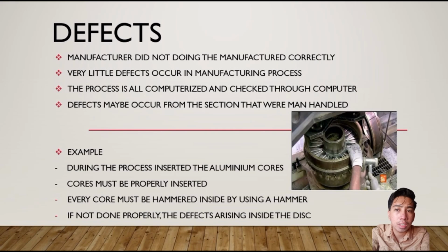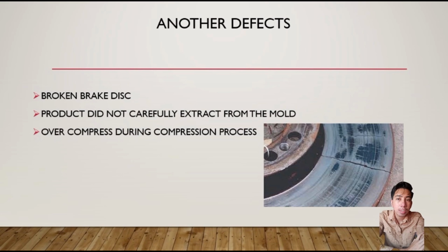In this manufacturing, there are defects that can occur from the section that were man handled. For example, when inserting the aluminum core into the mold, this core must be inserted properly and must be hammered inside using a hammer. If not done properly, there will be defects arising inside the disc. Next, other defects is broken brake disc. It can happen when the product is extracted from the mold, or this defect can occur when doing the compression process. If it was over compressed, the defect can occur to the product.